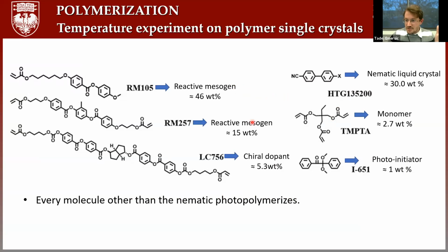And this mesogens, monomer, photoinitiator is for the purpose of polymerization. So our purpose is that once we form the single crystals, we shine the sample with UV light, and actually we want to freeze the system, right? And every molecule other than the nematic liquid crystal polymerizes.